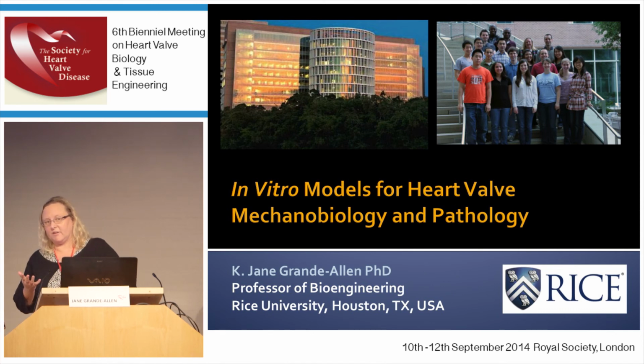Most of what I can comment on is related to how the cells have behaved in a hydrogel scaffold, and we have actually had a rather hard time getting those to calcify. So we're trying to examine this in more detail, but with classical osteogenic differentiation medium with dexamethasone, beta-glycerophosphate, and ascorbic acid, we have had a hard time demonstrating calcification as indicated by a calcium stain, like using Alizarin Red, for example.